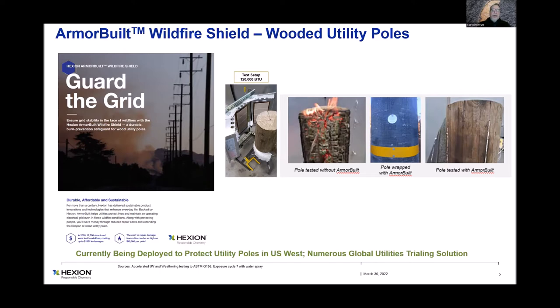We impinge three gas-fired burners onto the face of the material, and you can see just to the right of the burn apparatus an unprotected, treated pole section. It basically chars into ash until it goes away, and right beside that is a wrapped pole that one of the big utilities in California has wrapped right now. In fact, one of the larger utilities in California has wrapped over 60,000 poles just themselves.